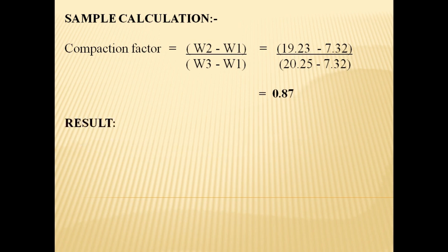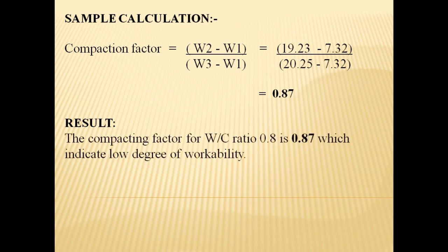Now we are going to see the result. So the result is the compacting factor for water cement ratio 0.8 is 0.87, which indicates low degree of workability.